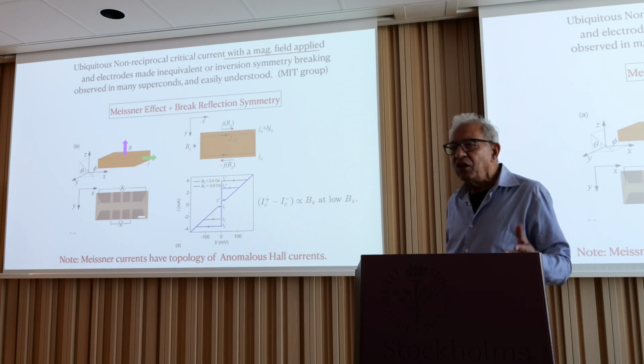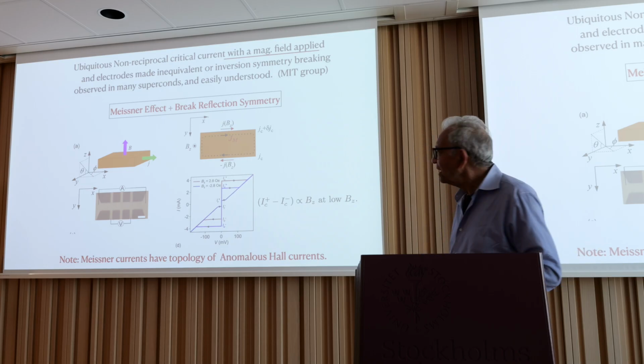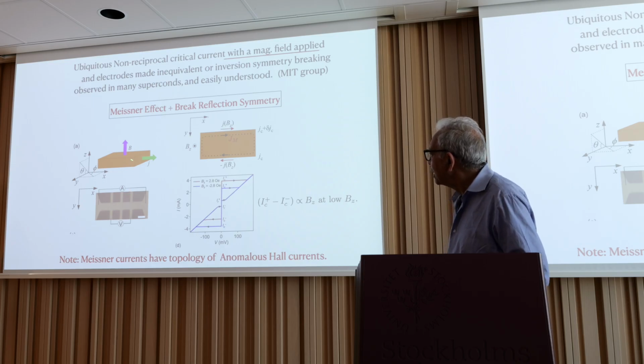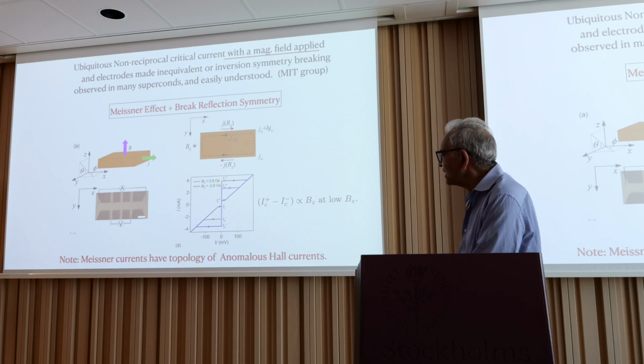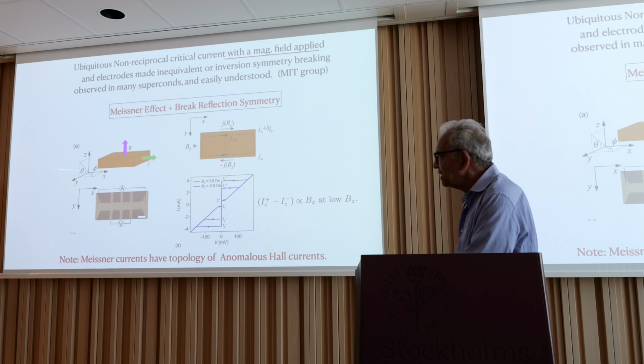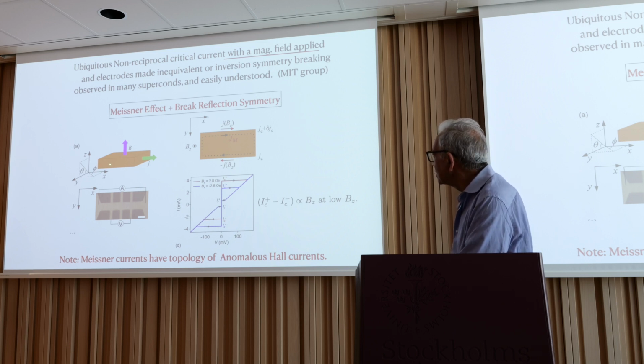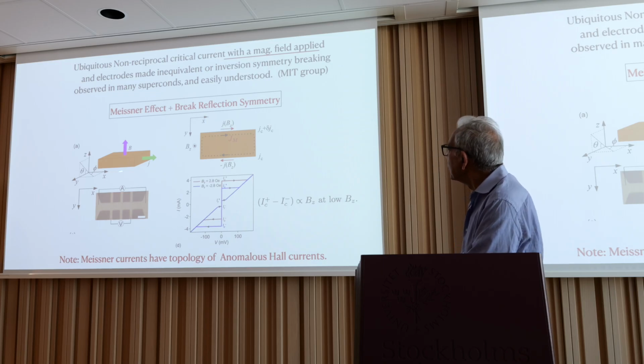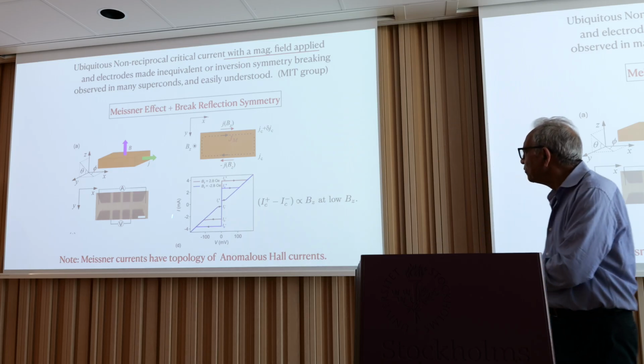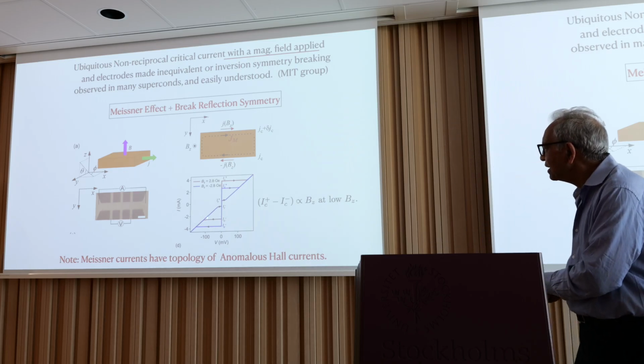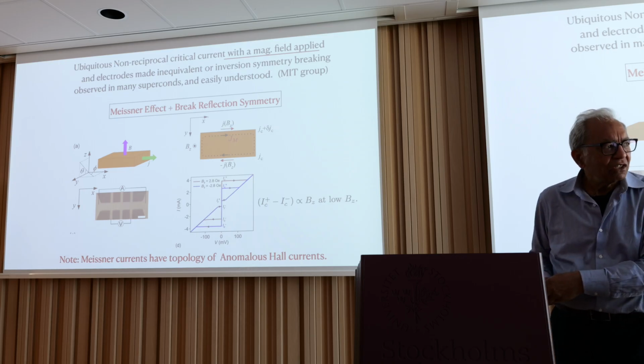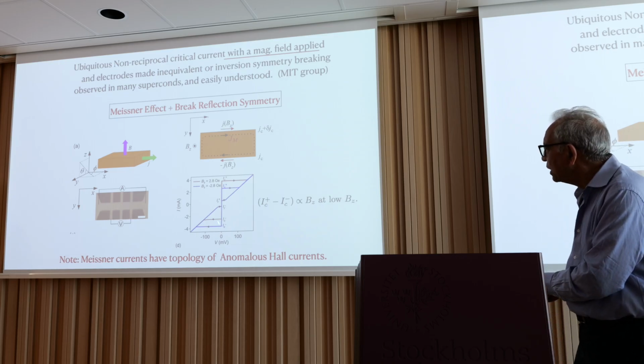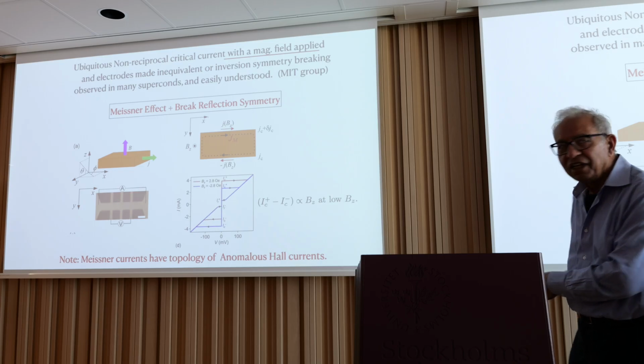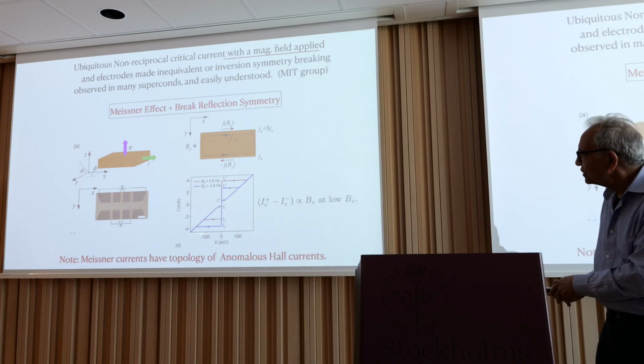Okay, so in almost any superconductor, you can apply a magnetic field and measure the non-reciprocal critical current. Here is an example from the MIT group. I've forgotten, this may be metallic niobium for all I know. Superconducting niobium. And you observe this IC plus and IC minus differing.